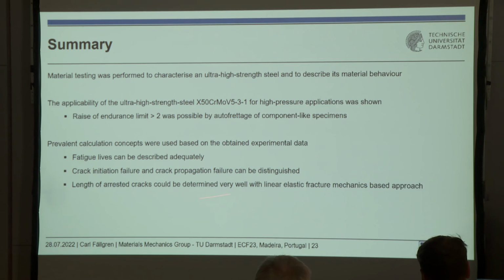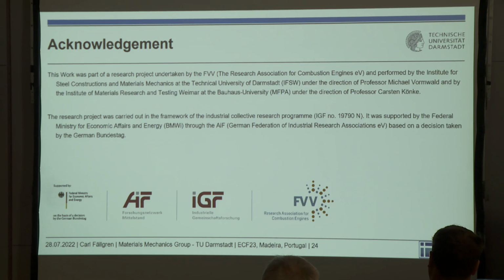Yeah, so summary, material testing was performed. We characterized this ultra high strength steel. The applicability is very good for high pressure applications, as we could show, and a raise of the endurance limit by a factor higher than 2 was possible for the autofrettage specimens. And with the calculations, fatigue lives could be described adequately, crack initiation failure and crack propagation could be distinguished, and also the length of the arrested cracks for the endurance limit could be described very well with the linear elastic fracture mechanics-based approach.